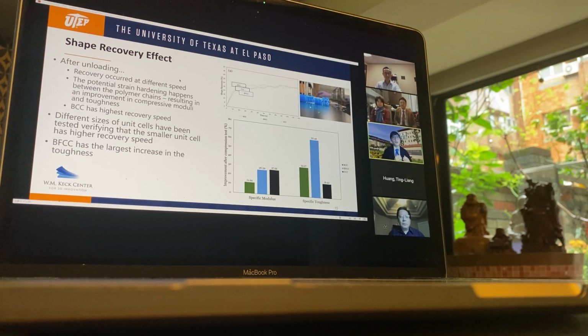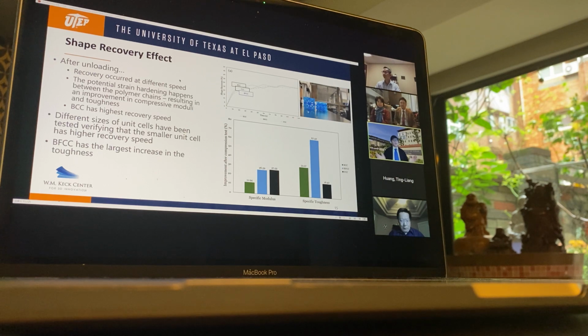Besides these patterns, we had one experiment before to test different sizes of the unit cell. In general, we understood that the smaller unit cell just needs to recover a small ratio of deformation after the compression. So coming back to the diagram, we use the assumption to explain why BCC recovers fastest, which is because the deformation will focus on the joints in the whole structure, which means the deformation will be uniformly divided into different layers. By this mechanism, the BCC pattern just needs to fix the smallest part to recover its shape.